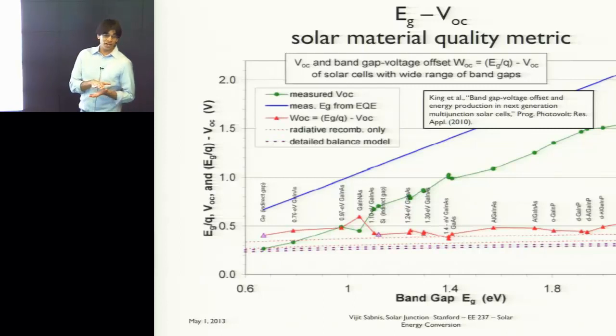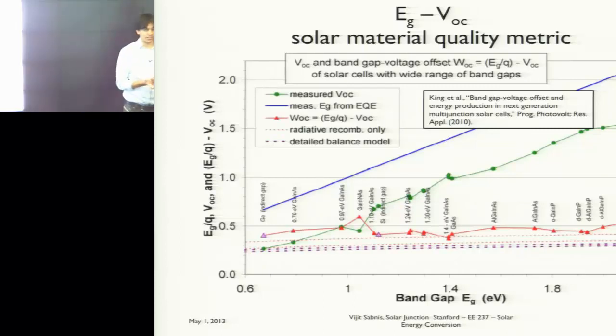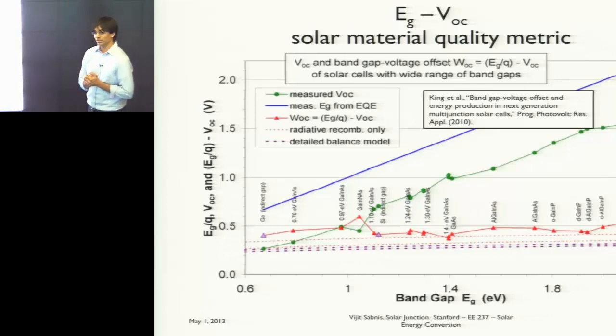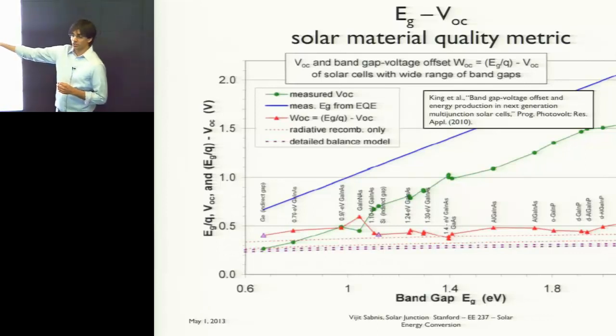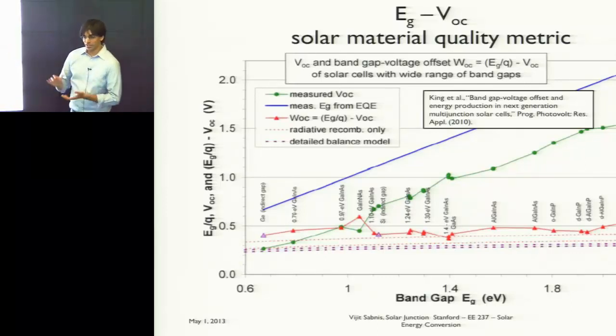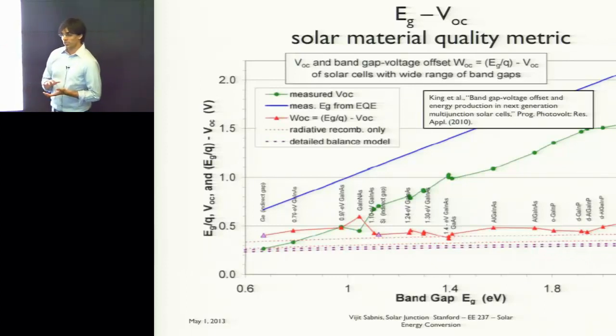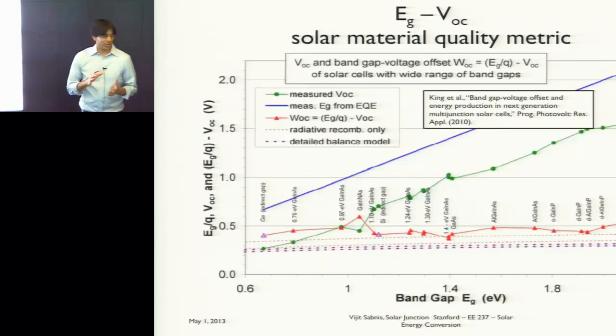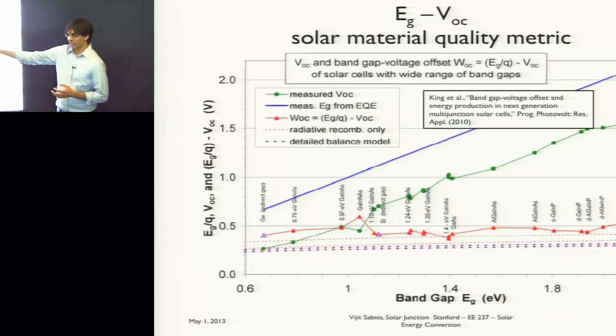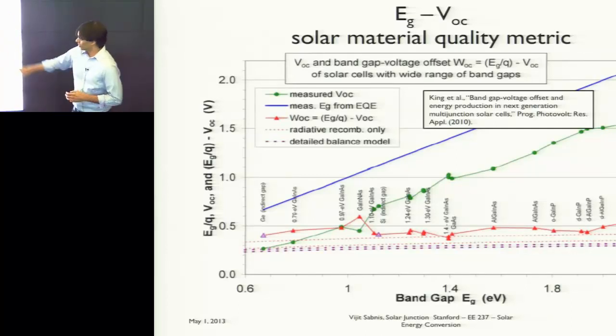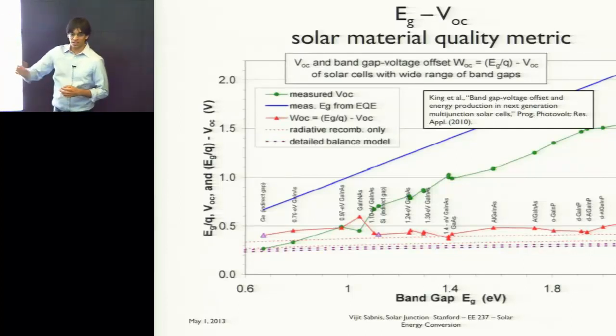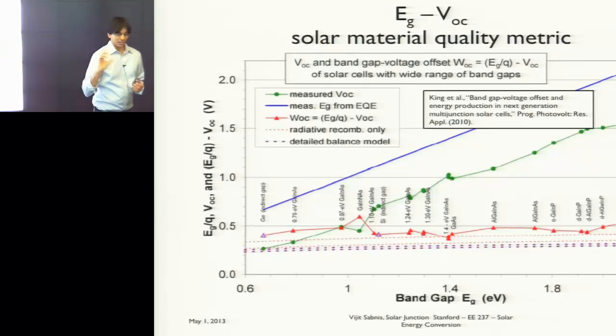In the Alta Devices configuration, because they have a back reflector, you can actually get that down to 300 millivolts. So one of the things we do at Solar Junction when we're developing a new material or a new band gap is we measure single junction solar cells with that material at 1 sun. And we know that if we're not down close to about 400 millivolts, that material is not going to be suitable for integration into a multi-junction solar cell. So this was a very nice study showing that for different materials there's a very good convergence to a delta of about 400 millivolts.